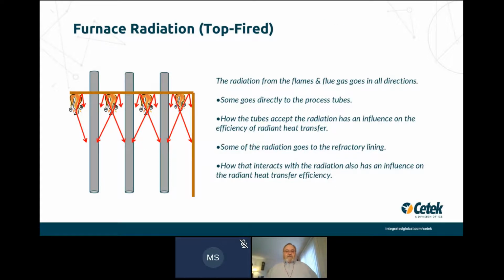This next one is a schematic showing a top-fired unit. There are many top-fired Kellogg design, KTI design units which have top-fired burners. Here you could see that the refractory coating on the side walls has an effect mostly on the tubes nearest to the wall. But as you go further inside the unit, the effect from the high emissivity coating on the side walls diminishes because the tubes shield themselves. And so the tubes in the center would get very little effect. The only effect is from the roof around the burners.